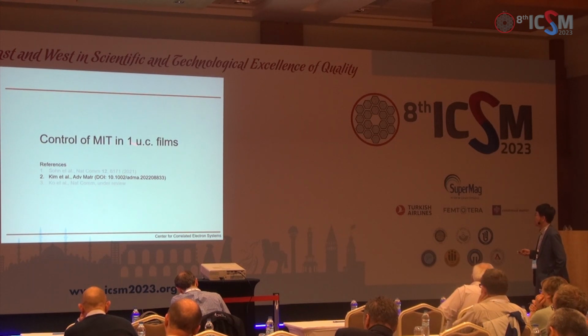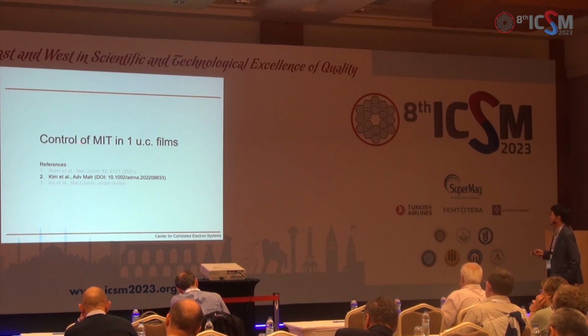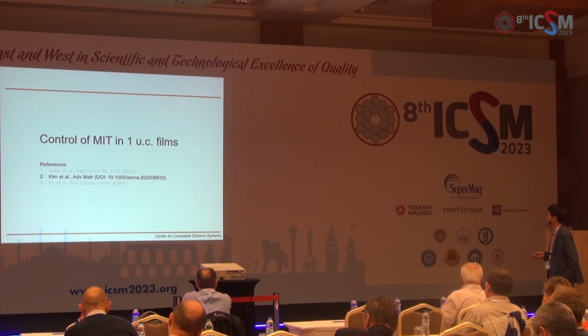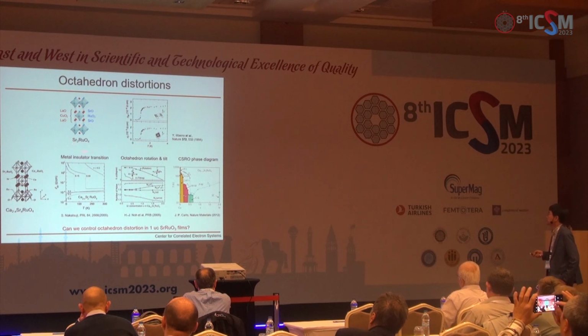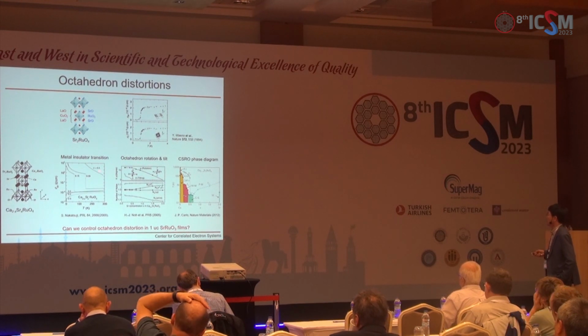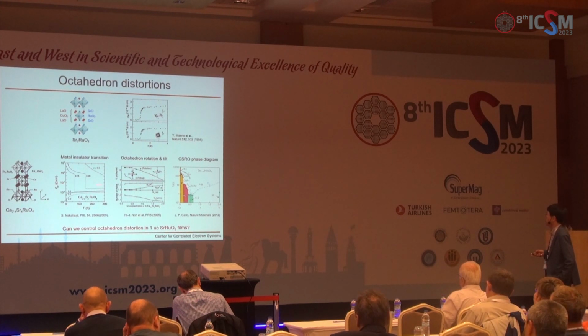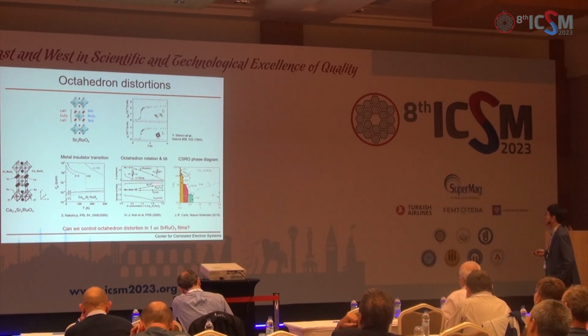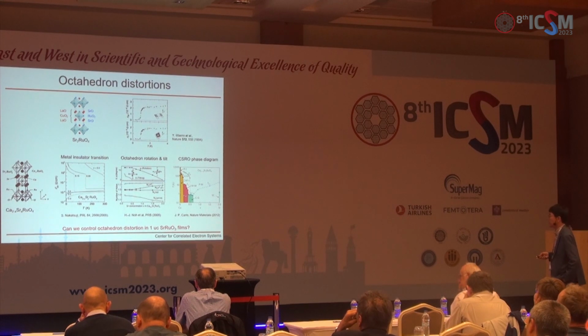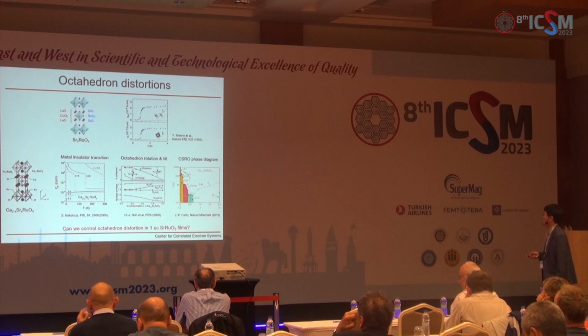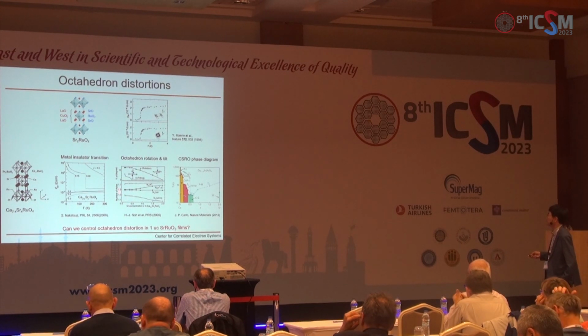Now, once we found out that one unit cell film is at the verge of Mott transition, we were thinking about whether we can control metal insulator transition in one unit cell. So let me show you earlier work on strontium ruthenate 214. This is a single layer system, and as you replace part of strontium by calcium, it goes through a very interesting metal insulator transition. It turns out that as we replace strontium by calcium, first it rotates the octahedron, then at a certain point it also induces octahedron tilting. And metal insulator transition, including orbital selective Mott transition, happens here. OSMT happens here, and true Mott transition happens around 0.2 or 0.15.